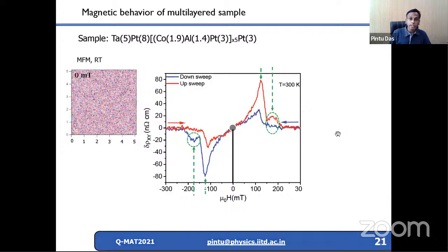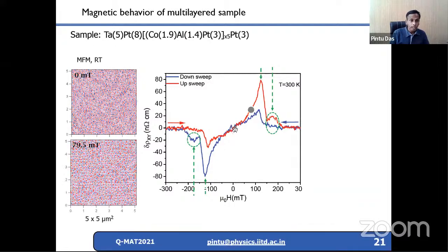Now if we look at the density, we wanted to look at the skyrmion density in this system. So we have performed magnetic force microscopy imaging at different fields. At zero field, there is no skyrmion, mostly worm-like features. That is a perpendicular magnetic anisotropy system, so this is what is expected. And the corresponding number in the topological Hall effect, the extra Hall effect, is almost zero here. Then as the field progresses, a few skyrmions develop around 80 millitesla. Our signal also improves here.